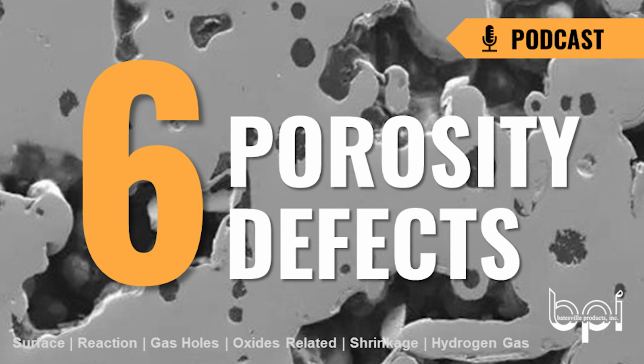And so the issue is how much can you stand when you cast? Do you want hydrogen or porosity-free castings? And if so, you need to degas. And the only way to get rid of the hydrogen in the molten aluminum is to degas. So this is just the degassing and degassing media, typically argon and nitrogen. The argon and nitrogen attach to the hydrogen and float it to the top.